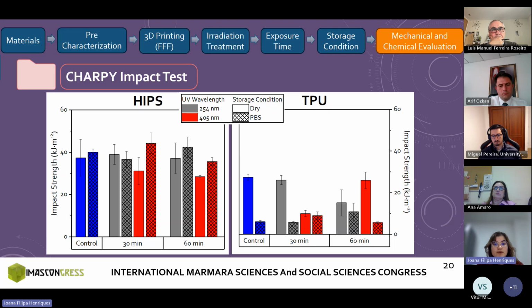In turn, TPU did not suffer visible damage because of its elastomer-like behavior, which justifies the lower values. Although the wavelength and the exposure time did not introduce differences in the results, the way the samples were stored did. While the presence of water increased the impact strength of HIPS, it has decreased this property in TPU.